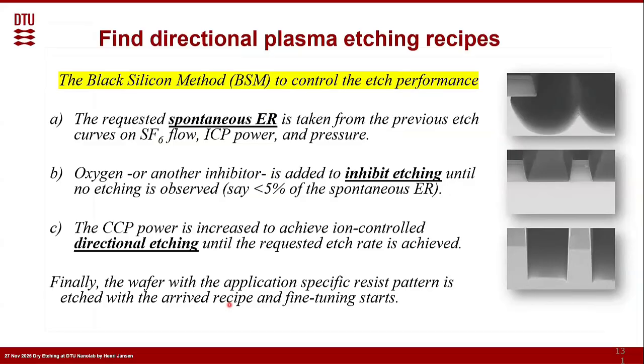It's very simple. So first of all, let's say we need a certain etch rate. Some people might say, I would like to have 10 micrometers per minute, and others who are much more in a nano world will say, no, I would like to have 10 nanometers per minute. But what we do, we just take the curves we have, and we find a spontaneous etch rate which matches with our favorable etch rate, be it 1 micron per minute or 1 nanometer per minute, it doesn't matter. You can tune that with SF6 flow, ICP power, and pressure, and then you have your number. And you put in your sample, and it should be isotropic, and hopefully the depth is exactly what you were aiming at, but you check.